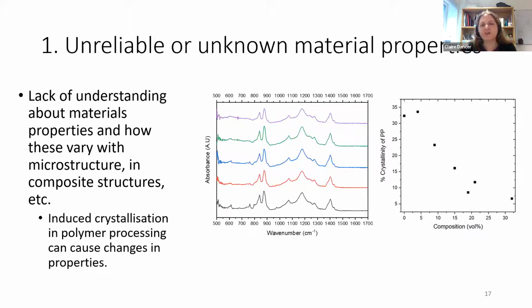So we found, for example, that this is some FTIR on PVDF with added ceramics. We're finding that we're changing the crystallization, we're getting a lot more beta phase PVDF, and it affects our properties. In this case, we're looking at crystallinity of polypropylene, which actually seems to go down as we add more barium titanate to the material, and that changes the properties again. So it's an interesting effect that we see in some of these materials.